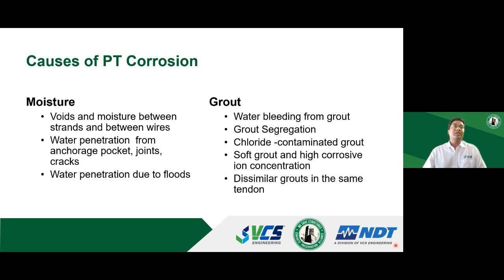And then on the other side, we have moisture and external contaminants, which can be introduced into the duct through end caps or through cracks in the duct. That can result in an environment that is very conducive to the corrosion of the post-tensioning strand. And I'll go over these concerns or causes in the subsequent slides.